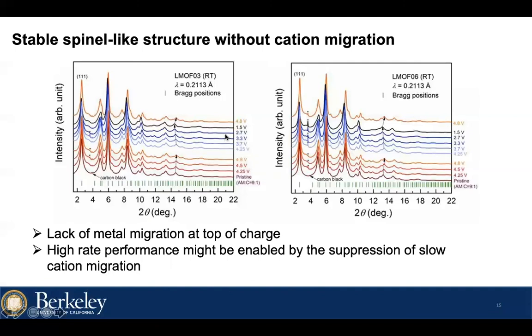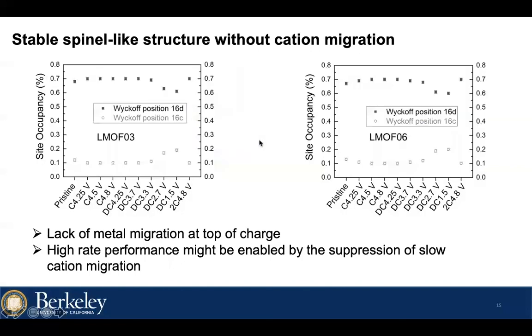To characterize how the structure changes during cycling, we perform operando synchrotron XRD measurements. From this data, we can refine the manganese occupancy to see whether and how the manganese can migrate. And here is the result. The manganese occupancy in the 16d site and 16c site is quite stable during charge and discharge, although there is a small change of the manganese occupancy at the bottom of the discharge. But it's not only small, but also reversible when it goes back to the second top of charge.